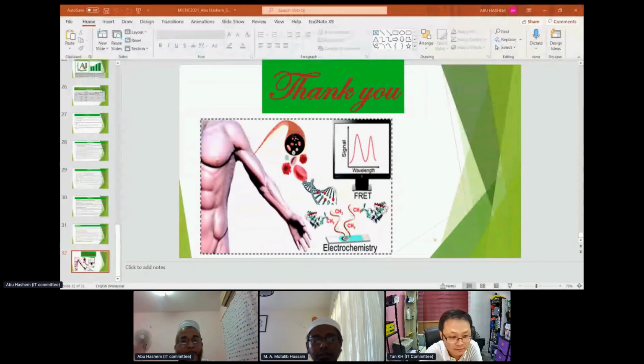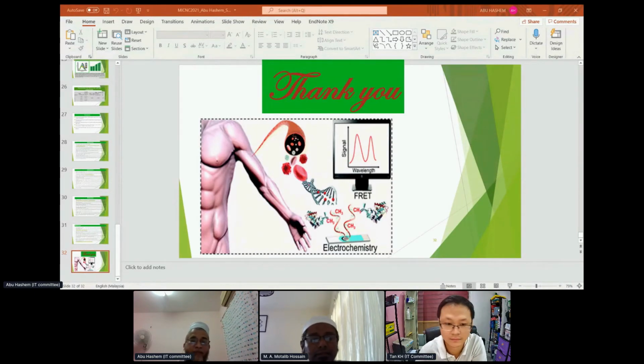Okay, thank you. My next question: why did you modify with gold and graphene oxide nanoparticles? Gold and graphene oxide are both very conductive, and they have a very large surface area. Due to the large surface, they allow binding of more DNA, and being more conductive, it increases our sensitivity. Besides this, we modified the probe with a thiol group so that it can make a strong covalent bond with the gold, and the sensitivity becomes perfect.